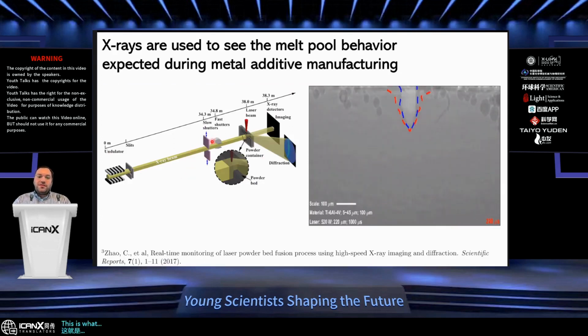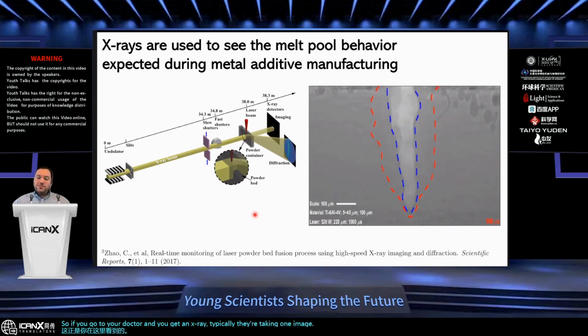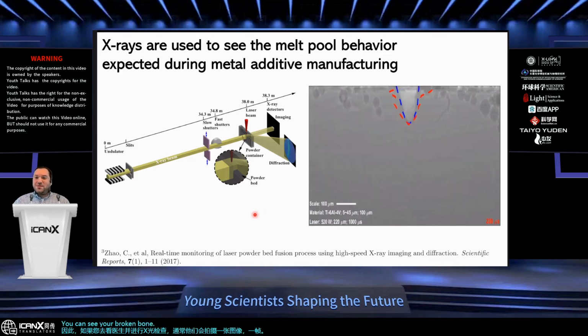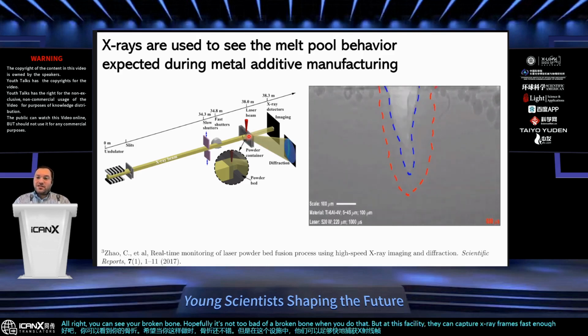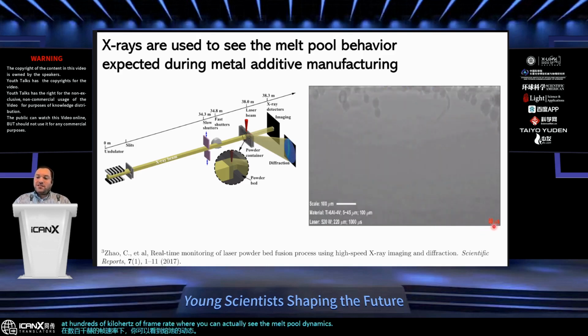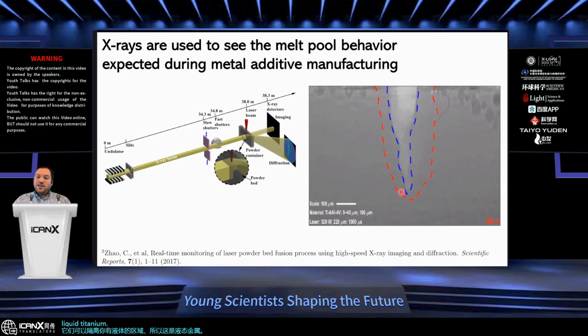This is a schematic of how the X-rays work. And so there's an X-ray beam that comes off of that circular ring. It passes through a thin sample, and it projects your melt pool onto a detector. And that's exactly what you're looking at over here. So if you go to your doctor and you get an X-ray, typically they're taking one image, one frame, right? And you can see your broken bone. Hopefully it's not too bad of a broken bone when you do that. But at this facility, they can capture X-ray frames fast enough at hundreds of kilohertz of frame rate, where you can actually see the melt pool dynamics. And so you can see the time scale here is in microseconds. And then the scientists that did these experiments, they can isolate the region where you have liquid. And so this is liquid metal, liquid titanium metal, and then the gaseous region, which is within the blue. Okay.